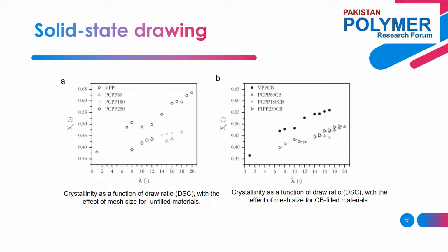It can be concluded that melt blending method, injection molding, dynamic injection molding, and solid state drawing method improve the properties of nanofiller reinforced polymers. Melt blending method improves the properties of polymer which are not affected by the water but can cause to degrade the hygroscopic polymers. Solid-state drawing method enhances the properties of filled polymer by improving the crystallinity and chain orientation of polymer matrix, but the utilization of drawing line make it complex and expensive operation.